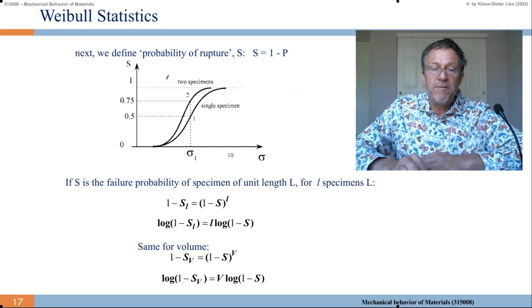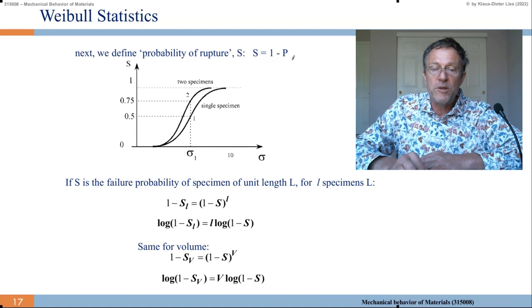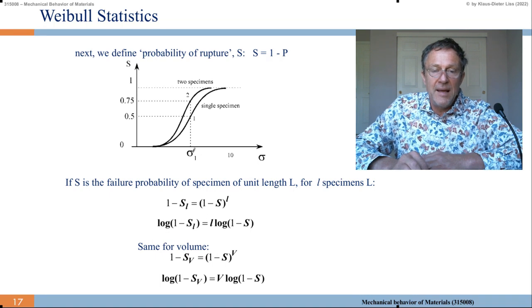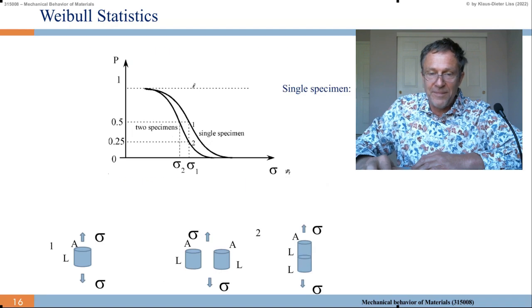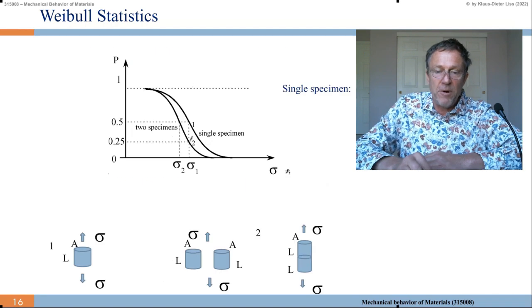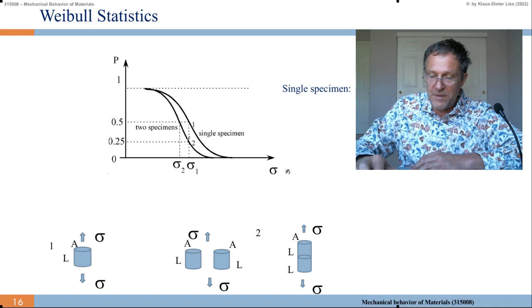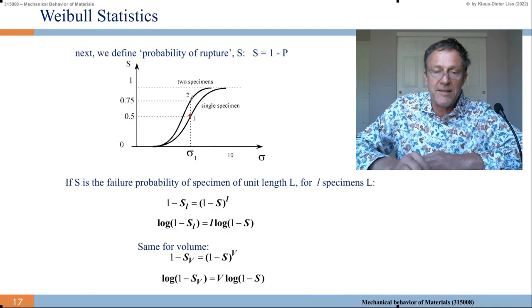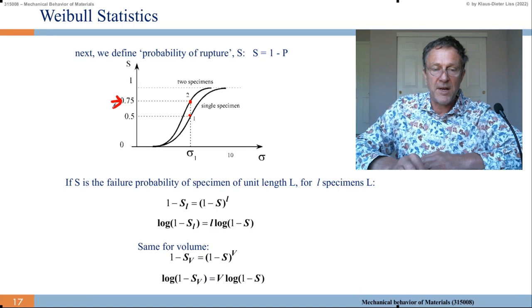So now let's define the probability of rupture. S equals 1 minus P. And then, of course, we get the inversion of this curve, 1 minus P. Probability of rupture, let's say at sigma 1, I get the point 1 here. And at sigma 2, I have to take 1 minus the point 2, which was 25%, so I get 75%, 0.75 for the probability of rupture.